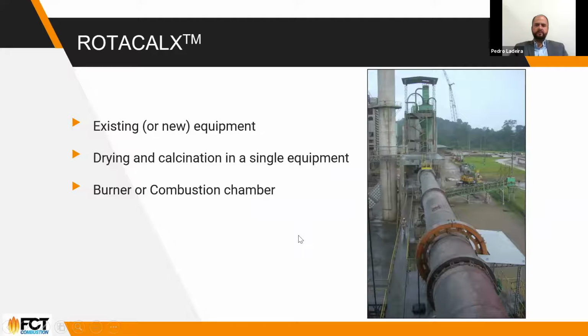The interesting thing about this technology is that we can combine drying and calcination in single equipment. Of course, we're talking about drying from, say, 35% moisture down to what's necessary for calcination. But if you don't need an auxiliary drying up front, we apply a burner for a main source of heat, and also we can use a combustion chamber to fire the process depending on the specifics of the project.